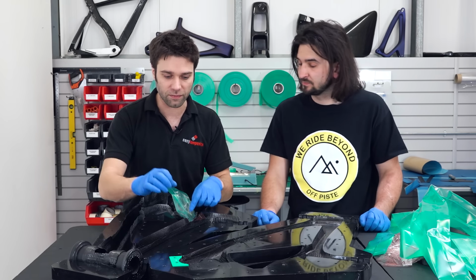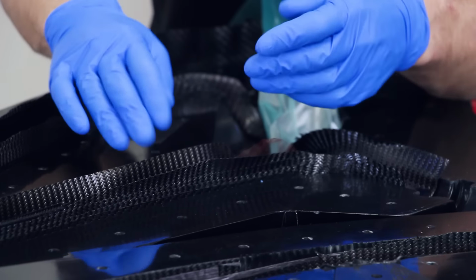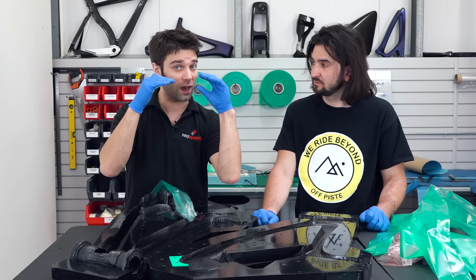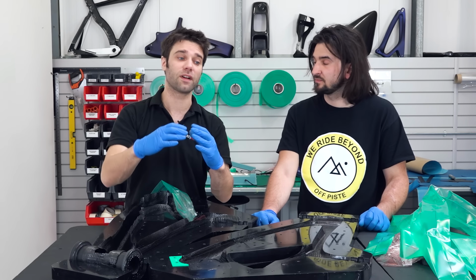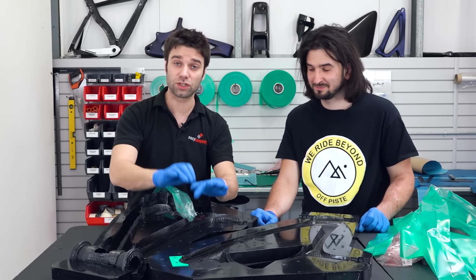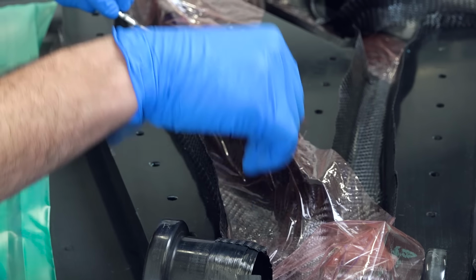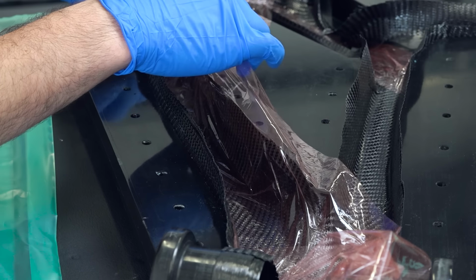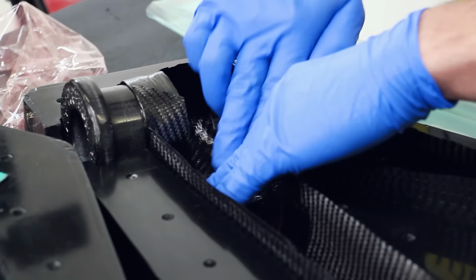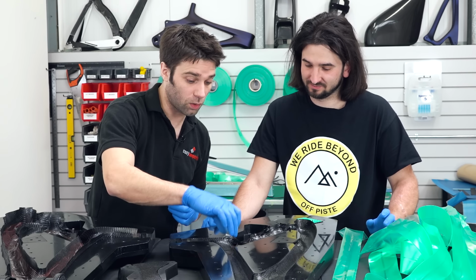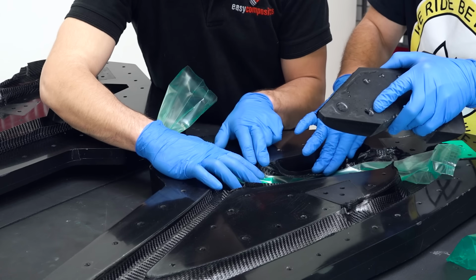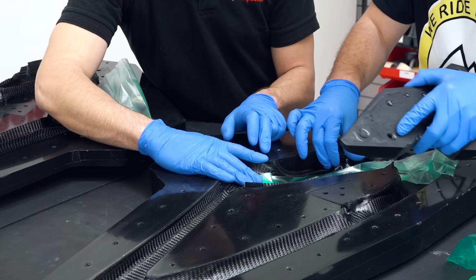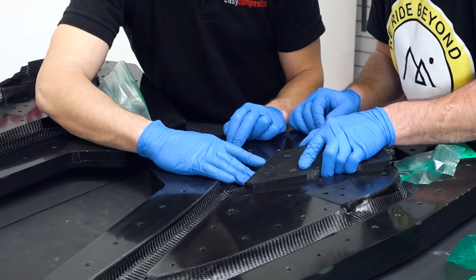The real thing to be careful of here is that you don't get any release film going onto the wrong side of your lap. If you get a bit of release film between the lap and the other side of the frame, you're going to have no bond strength whatsoever, and that could be a potentially very dangerous situation to be in. So the release film is just going onto this one side, the side with the laps, and then there's no risk of it subsequently getting into the gap. So the first bag is going to be the one on one side of the shock tunnel here. Yeah, that's correct, and then we close the insert. So it's very important to make sure that all of these laps don't get trapped underneath the edges there.